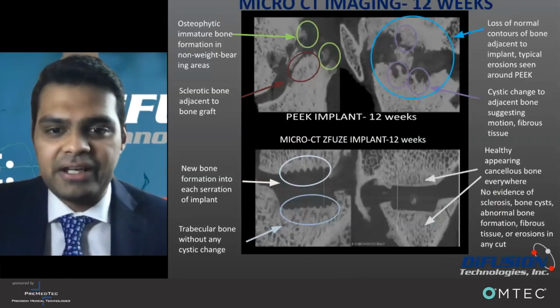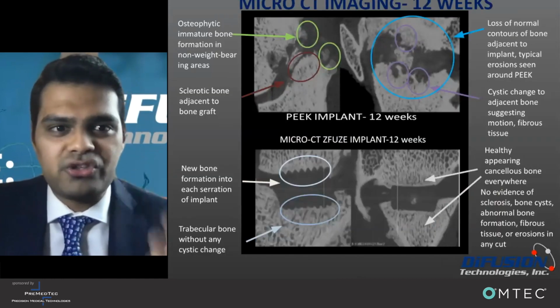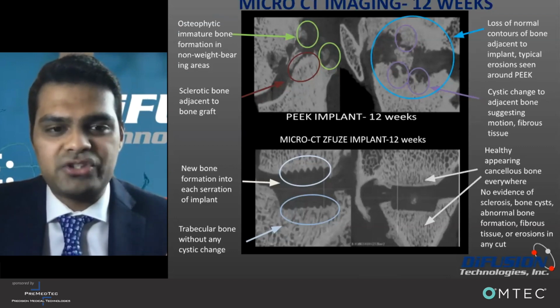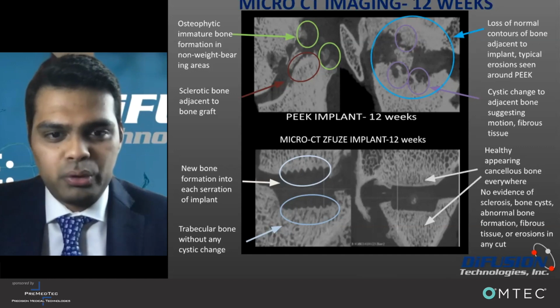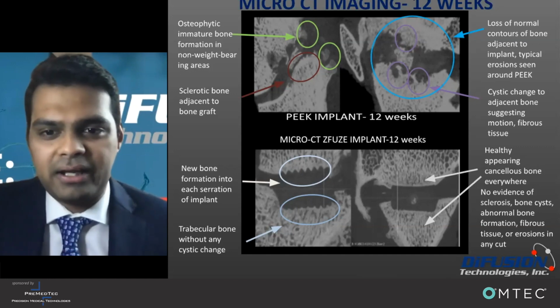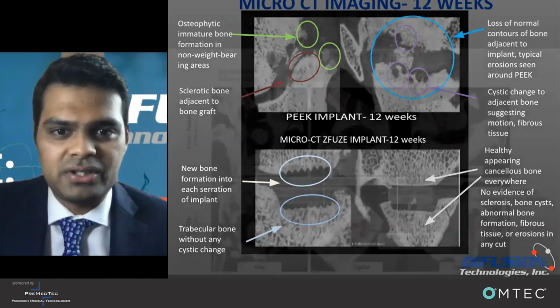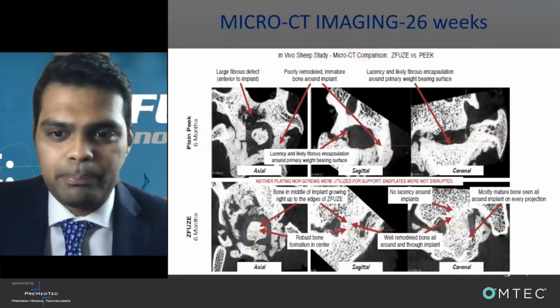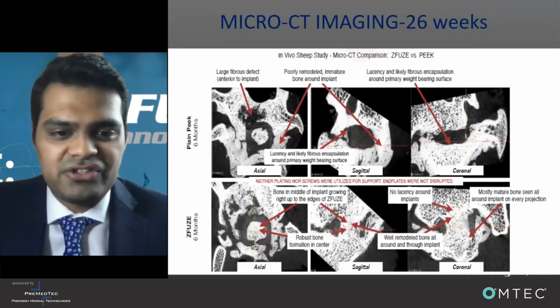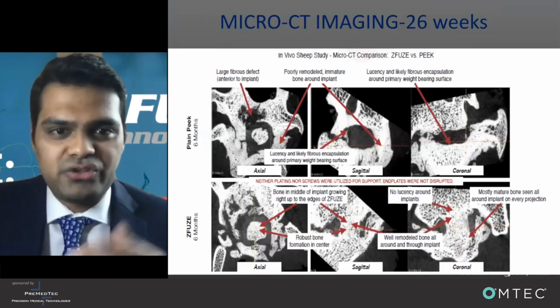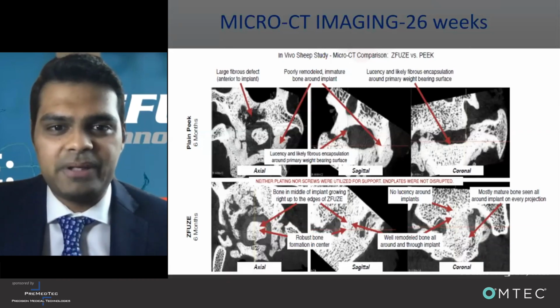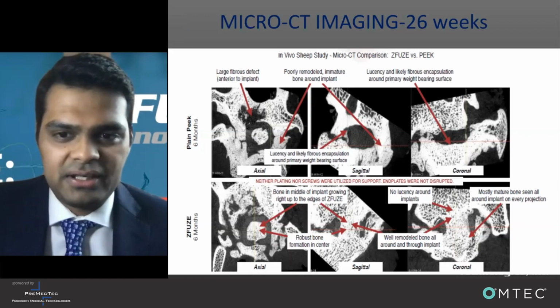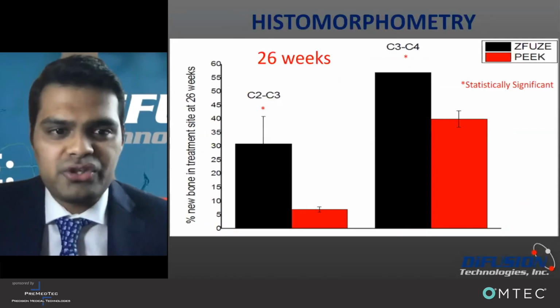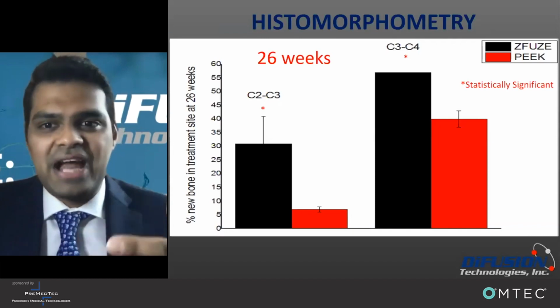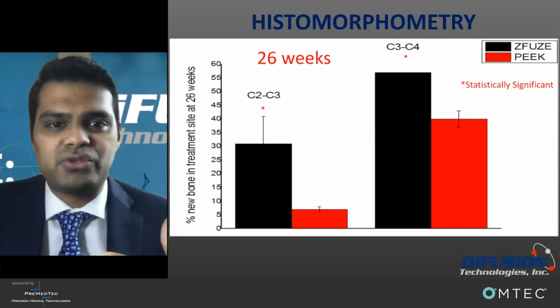And also that resulted in very interesting bone response. You can see that there was osteophytic immature bone formation in the case of PEEK at 12 weeks, whereas down there, you can see that new bone formation beautifully into the teeth of the implant was seen. Healthy looking cancellous bone everywhere on ZFUZE at the bottom at 12 weeks. At 26 weeks, look at that at the bottom. Just a beautiful fusion that's seen in the coronal plane as well as sagittal and the axial plane, all three planes. Whereas you can see that there was a fibrous defect in the case of PEEK and kind of fibrous encapsulation and lucency around the implant was seen. And so what we also saw was bone ingrowth that was exaggerated in the case of ZFUZE relative to PEEK at 26 weeks at both sites.